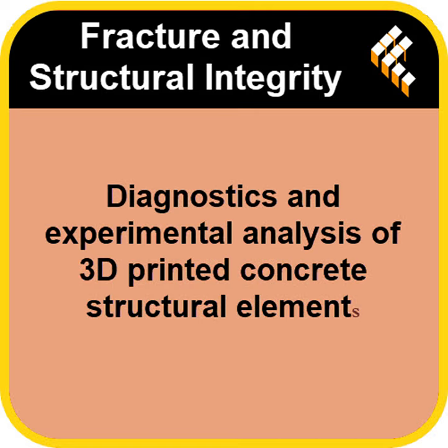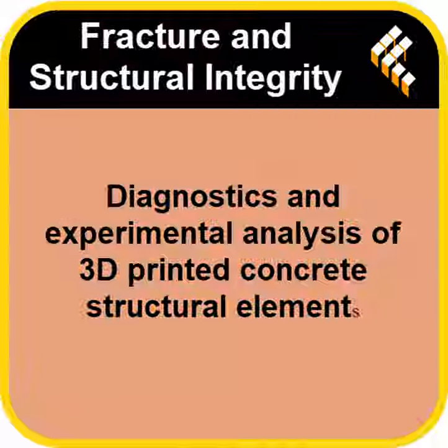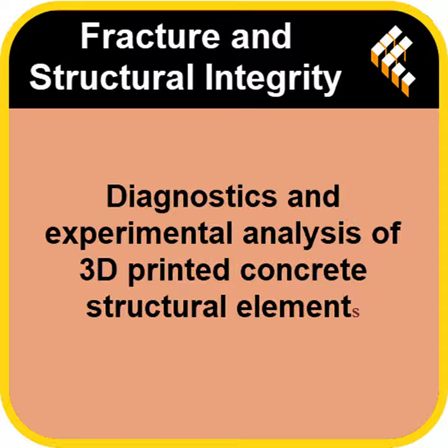And they put all 6 of these columns into a 3-point bending test, basically pushing down on the middle until they broke. And the results were, well, they were alarming. They were. The difference wasn't just a number. It was the difference between a gradual, predictable failure and a catastrophic collapse. Wow. 3 of the columns showed a gradual bending failure. You could see a crack slowly developing at the base.